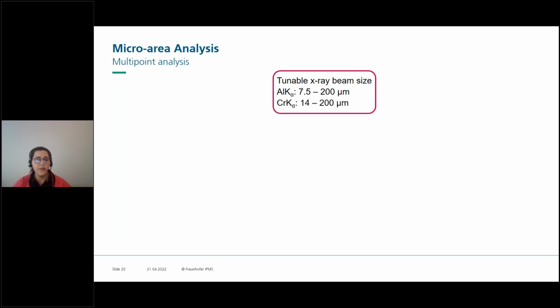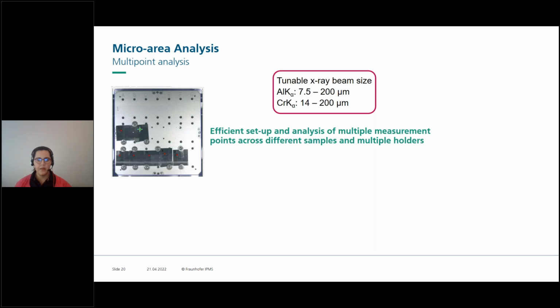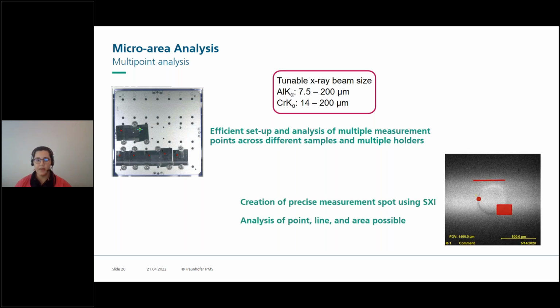Since we can tune our X-ray beam size, we can do microarea analysis. For aluminum Kα, we can tune it between 7.5 and 200 micrometers, and for chromium, between 14 and 200 micrometers. This can help us with efficient setup and analysis of multiple measurement points across different samples and multiple holders. And it can also, in addition to SXI, create precise measurement spots.